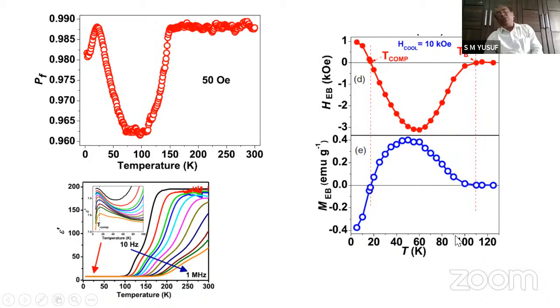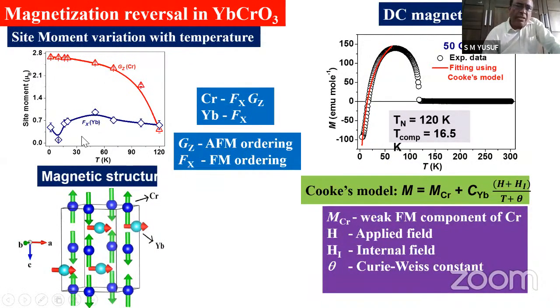So here I would like to tell you that over recent years, since we have already established the magnetization reversal phenomenon, now we are trying to see the cross correlation, whether the magnetization reversal or magnetization compensation has any consequence with other physical properties. And that is indeed shown here, that exchange bias is very much coupled, one-to-one correspondence. Even here you see the dielectric constant. Here also this is a compensation temperature, you see the one-to-one correlation. So this kind of novel correlation of different physical properties across the magnetic compensation temperature has been established in recent time by us.